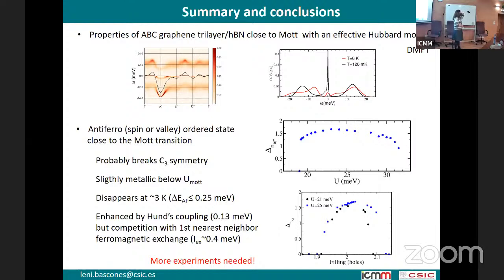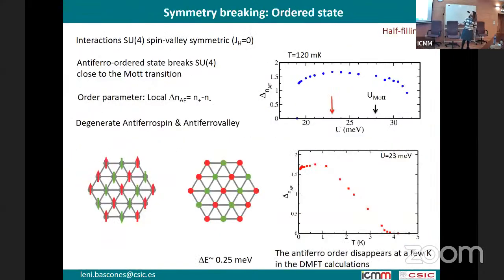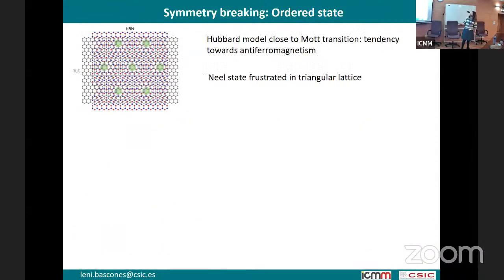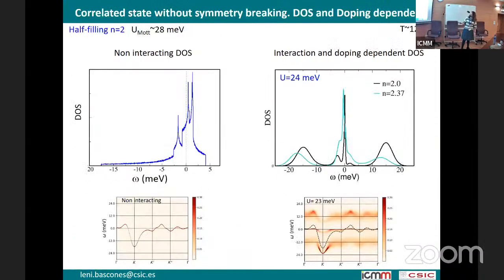So you were discussing that as you increase the Hubbard interaction, there is the emergence of this coherence peak in the spectral weight. What is the actual role of this emergence of the coherence peak in the phases that you are studying? Because this is something that I missed. Yeah, the strong renormalization of the bands is clear, but the coherence. What the coherence is telling you is that you have a quasi-particle band.